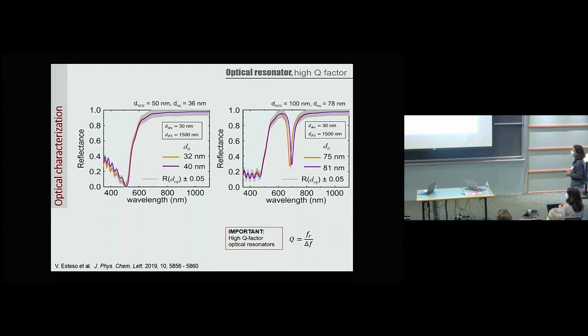One strength of our design is that you need high Q factor optical resonators to really say that what you are observing is levitating. Otherwise, what I'm showing here in gray is the reflectance with 5% error, which could arise from anything in the experimental measurement, and you could not distinguish systems that are levitating from those that are not levitating, which are these other curves. Whereas with a high Q factor optical resonator, this is accurately described, and just one set of parameters is going to fit your optical response.